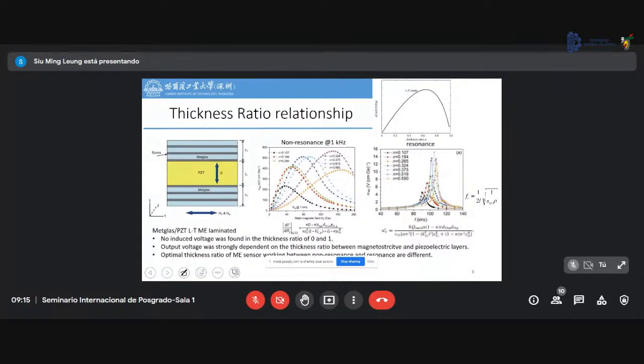This is the thickness ratio relationship of our material, and there are some equations for the calculation. For our material, in the non-resonance and resonance regions, there are different optimum thickness ratios. The best one is about 0.5 in the non-resonant region, but for the resonance part it is 0.3 or 0.4. So for different applications or materials, we need to consider a different thickness ratio when we want to make a sensor or actuator.